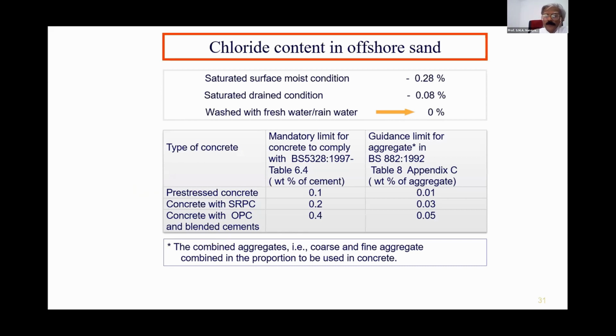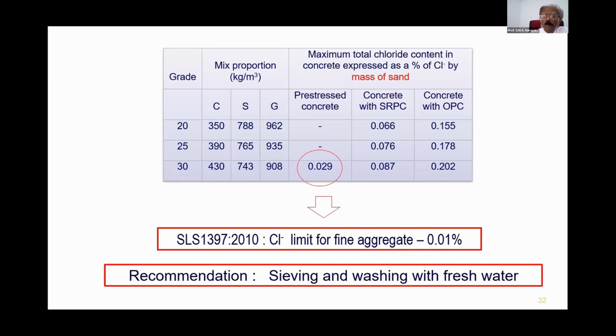The biggest problem is the chloride content in offshore sand. As it is, it contains about 0.28%, and if you wash it, you can remove these chlorides. And if you refer to the standard for concrete and standard for aggregate, there are limits specified for chloride content in concrete depending on the type of concrete. And if you convert these limits to maximum total chloride content in concrete expressed as a percentage of chloride by mass of sand for different grades of concrete, you can come up with these figures.